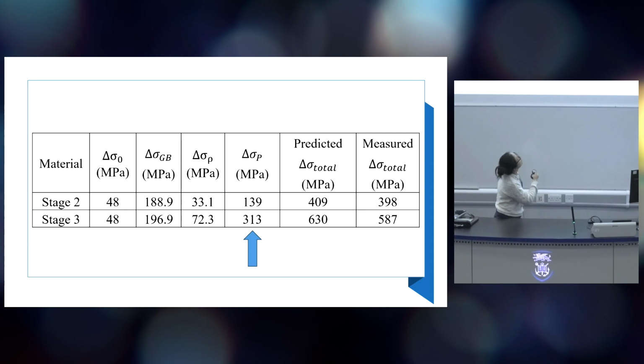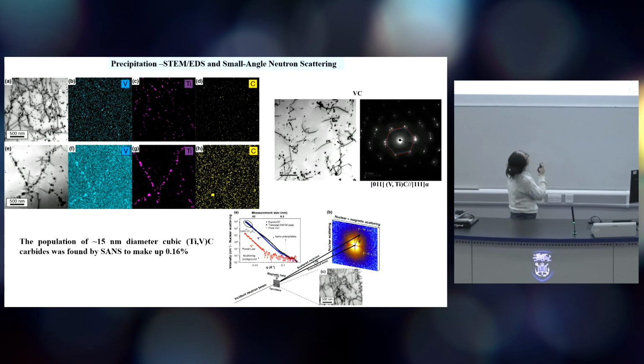We calculated the yield strength contributed by grain boundaries, dislocations, and precipitates. From the results, we can find that the precipitates contribute half of the strength, which means that the strength was improved by the precipitates, and the ductility improved mainly because we achieved bimodal structures. We also analyzed the type of the precipitates through EDS and diffraction. These nanoscale precipitates in the ferrite phase are mainly titanium vanadium carbides.